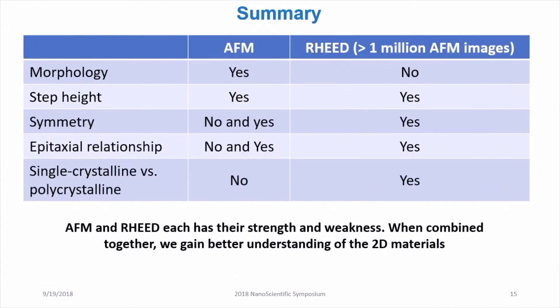To sum up, I'd like to give a comparison between these two techniques. For AFM, we can certainly do very well in terms of morphology and determining the step height. For symmetry and epitaxial relationship, that is harder and depends on whether you can get atomic resolution.